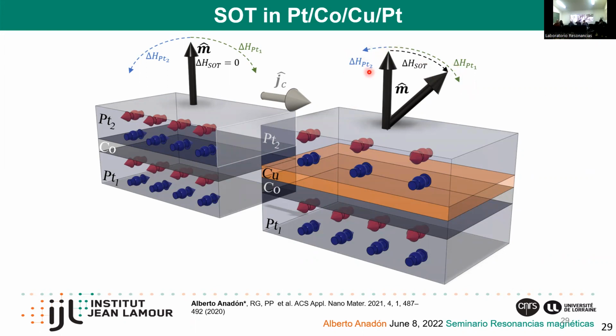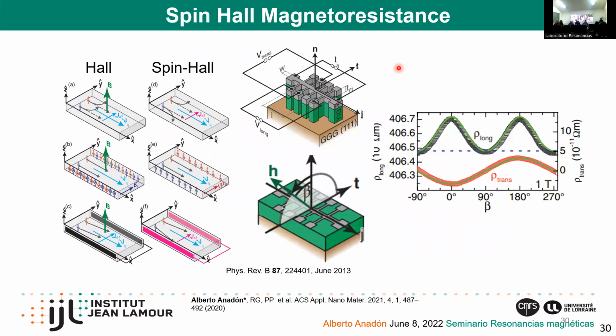So to understand what's going on in the system, we studied the spin Hall magnetoresistance. And the spin Hall magnetoresistance is a double spin conversion process. So we have at first a spin Hall effect in the platinum layer, and also inverse spin Hall effect coming back to this. And the combination of these both effects is giving some changes in the longitudinal resistance of our sample.